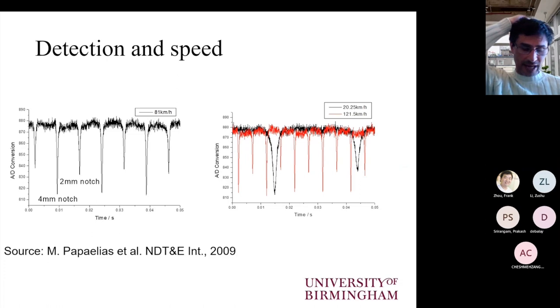The same applies for eddy-current testing. Unfortunately, if it was MFL, at this kind of speed, you would not have seen much of a response, especially from the smaller defects. They would probably have disappeared altogether. You might have been able to detect, but not reliably, the larger defects. But in this case, we would have grossly underestimated.